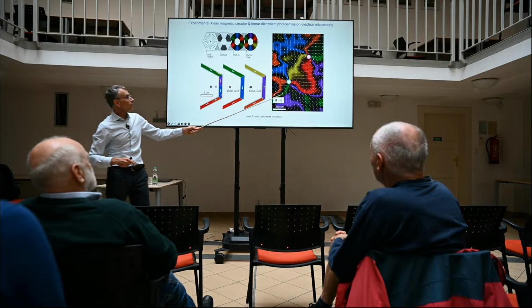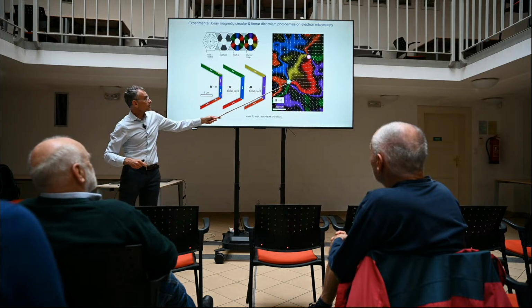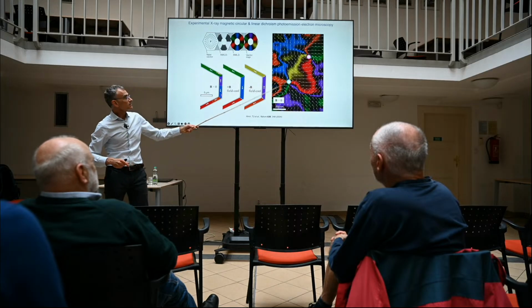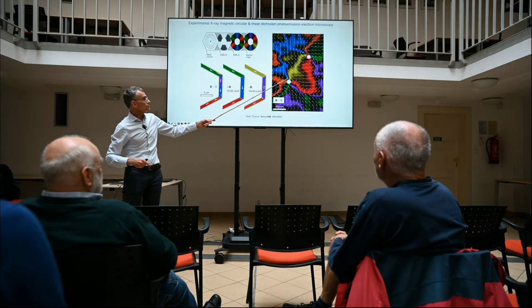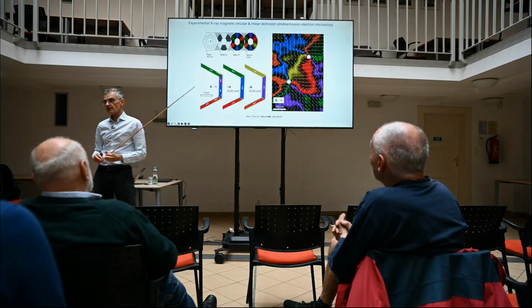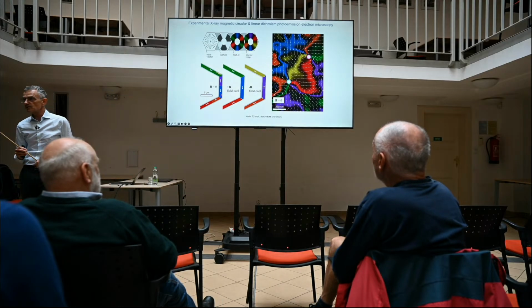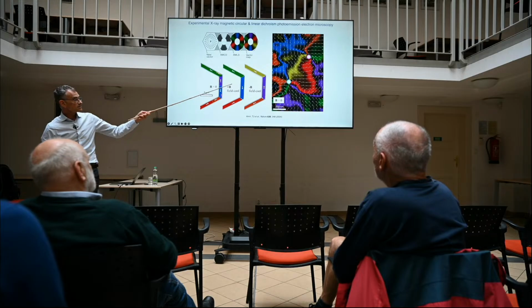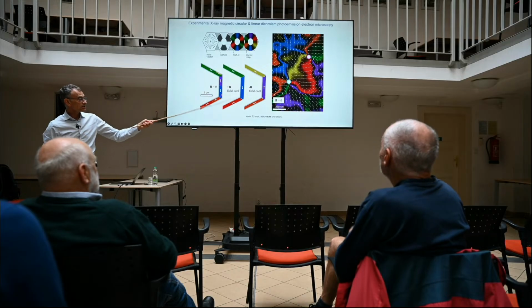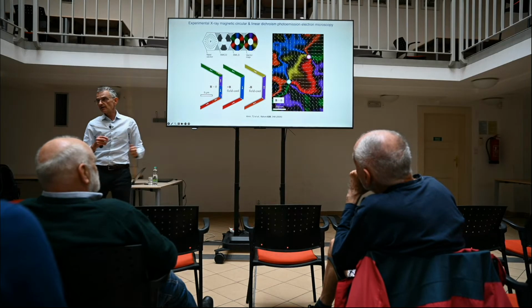And this is before it was prepared in the single domain state, so it shows that you can have domain walls, you can have these topological vortices and all that, which is another topic in magnetism which is quite interesting. But the remarkable thing is that this is a compensated magnet, and we can now image it down to 10 nanometer resolution.